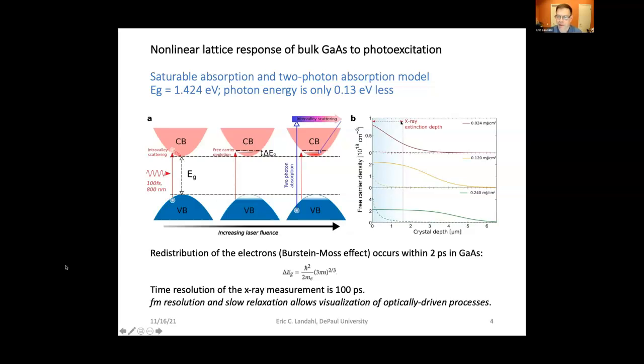The probe depth with perfect crystals is given by the X-ray extinction depth, which is right about 1.5 microns. So we're essentially averaging over this area, and because it's a very smooth curve, we'll get back to that later, that means that the diffraction peaks that we observe are also very uniform and uniformly shifted, but not greatly broadened or distorted at first. As you continue to increase the laser fluence, here up to 10 times the initial value,